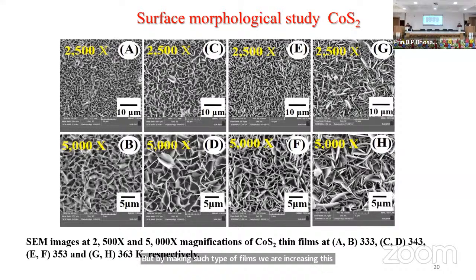As you know, when you talk about thin films, the geometrical surface area could be 1 by 1 centimeter square. If I make a deposition over 1 by 1 centimeter square, this will be its geometric area. But if you go for its actual surface area, it could be 10 raised to 2 times or 10 raised to 3 times greater than the geometric area. And now, we are also making modifications by controlling the reactions, by adding some complexing agents. I can have control over the morphologies, and I can get different types of morphologies.